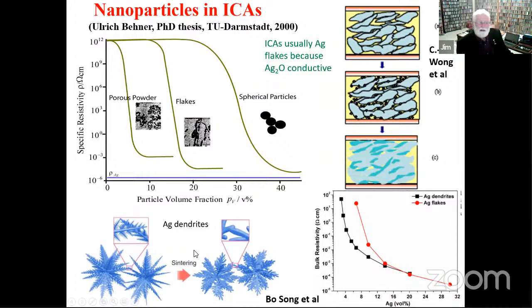This idea is being moved forward, and so you can grow dendrites on silver particles, and these have this sort of shape here so that they will sinter together and form bonds. So this is the thing here with dendrites. Either you can get a given resistance at a smaller concentrate amount of silver, or you can get a lower resistance for a given amount of silver.